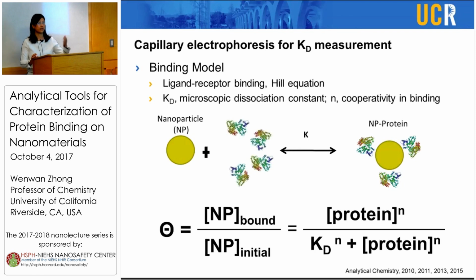So what we use is a separation-based technique. It's an open channel separation, so we don't have any gel or packing material inside the capillary column. Therefore, there's no interruption of the binding, which is a non-covalent interaction. Our model here is that when the protein binds to the nanoparticle, it will change either the size or both the size and charge ratio of the complex. So then we can see an electrophoretic mobility change of the particle itself.